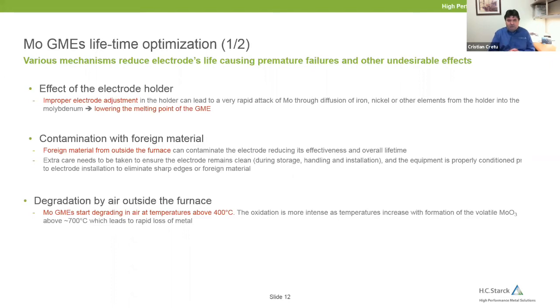And here in the next two slides, there's 6 of them. Effect of the electrode holder on lifetime of the GME. Improper electrode adjustment in the holder can lead to a very rapid attack through diffusion of other elements from the holder into the molybdenum. These elements typically lower the melting point, render the material softer, hence it's not as resistant to creep, sagging, and convection of the glass.